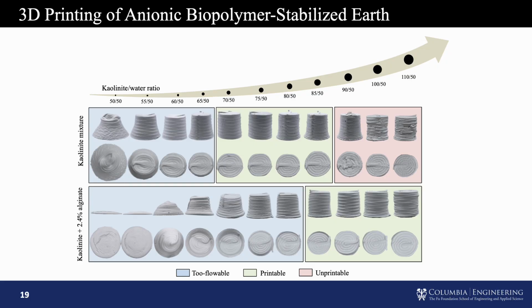Let's see how different clay to water ratios and sodium alginate addition affect the printing status of our material. The first row here is pure kaolinite. All of them are pure kaolinite mixtures. And the second one is kaolinite plus 2.4% sodium alginate. From left to right, we simply increase the solid volume fraction, or reduce the water content. Basically, when you have too much water, your material becomes too flowable. It cannot hold its shape. It is going to yield. And then at a specific clay to water ratio, your material becomes nicely printable, right? Eventually, if you keep reducing the water content, your material becomes unprintable and cannot continuously extrude from the nozzle.